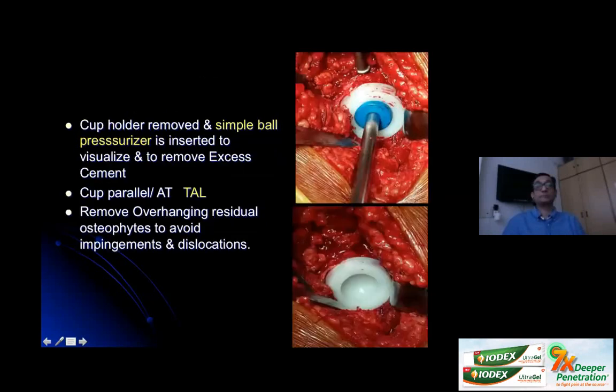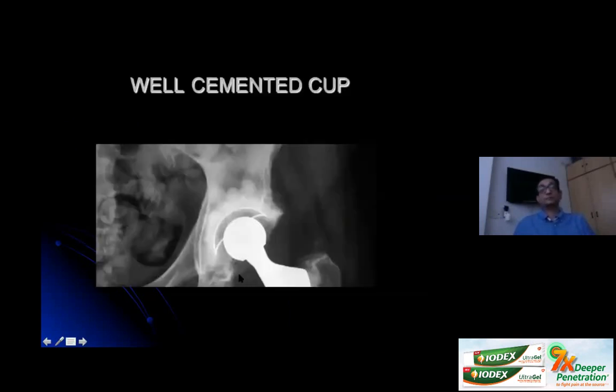After that, you remove your pressurizer and use the cup holder system as a pressurizer till the cement cures completely. You can remove the excess cement all around. See to it that your cup is resting parallel to the TAL (transverse acetabular ligament) at this time, so that you know that the inclination of the position of the cup is perfect. After your cement cures completely, remove all the overhanging osteophytes or cementophytes if there are any, so as to prevent impingement and dislocation later on. So if you do all this well, you can end up with a nice cup with a good cement mantle.